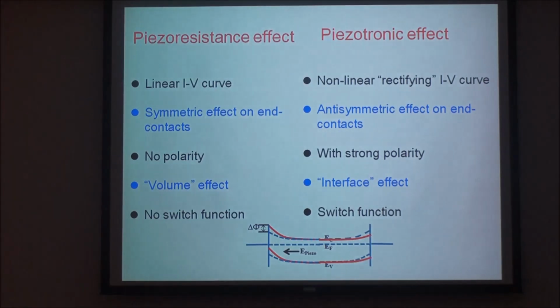this way. What's the difference between this piezotronic effect and the piezoresistive effect? We are very familiar with this one: carbon nanotube, silicon, used as strain sensors. This is a linear IV curve. This is a nonlinear, rectifying IV curve. This is symmetric. What does that mean? It's a resistance: whether the electrons flow this way or that way, it's the same. There's no polarity, but this one does, because you raise the barrier height here and lower the barrier height here. This has different effects. This is a volume effect, and this is an interface effect, because right here the polar charge sits here. This has no switch function; this will have a switch function. Those are the different effects of the piezotronic effect.